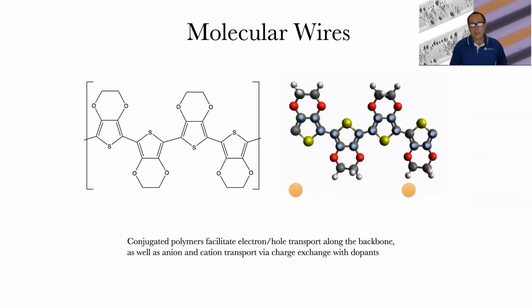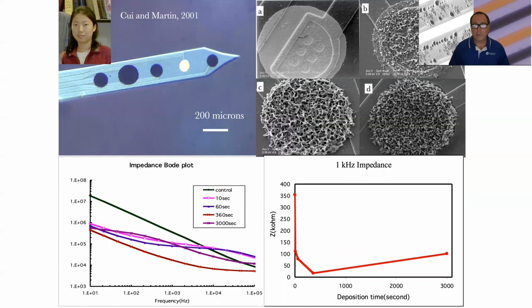If you look at the deposition of conjugated polymers onto a device as a function of time, this is a particular device, a Michigan-style neuroelectrode, about 150 micron wide silicon substrate with metal electrodes 40 microns in diameter. You send different amounts of charge through it, and you will deposit more and more conjugated polymer as more current runs through the electrode. If you look at the impedance of these electrodes, and we like to look at the impedance as a function of frequency, do what's called impedance spectroscopy. For biomedical devices, the important frequencies are those that are at 1,000 hertz and below. A neural event is typically 1 millisecond in length.